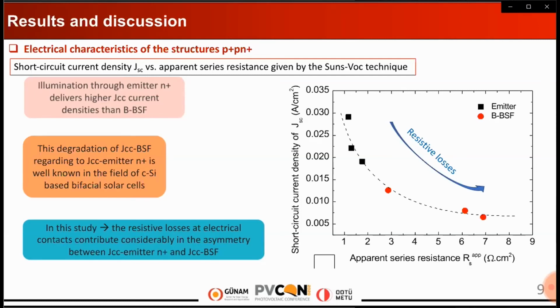From an electrical point of view, the deterioration of the quality of contact between the front and rear sides can be expressed by an increase in the series resistance. Indeed, the findings illustrated in this figure show an exponential decay of the current density with the increase of apparent series resistance. We have to note that the value of series resistance is directly determined by the Suns-VOC technique. These results demonstrate the detrimental effect of the series resistance on the current delivered by the solar cell during its operation.